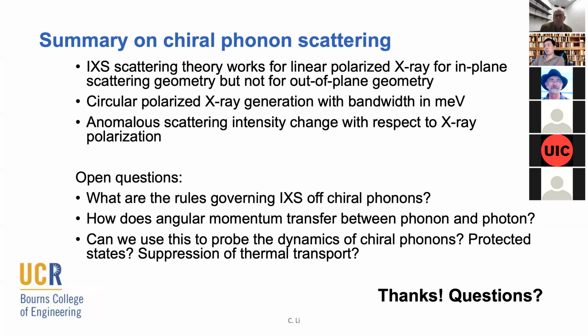So if this allowed us to look at chiral phonons, and we can see that, then we can spend more effort understanding their dynamics and what they can do in terms of phonon-phonon interaction. But right now, even trying to figure out the scattering rules governing the process is tricky with the limited statistics we have. For example, we only look at the K prime point, and to get a good idea of how it behaves, we have to go elsewhere. But elsewhere, the phonons will have much lower circular character, so the contrast will be even lower. We probably won't even see an effect at those places. So the flux would help, and we could also work with a more focused beam that is more beamline specific, inside of the overall update to the facility.